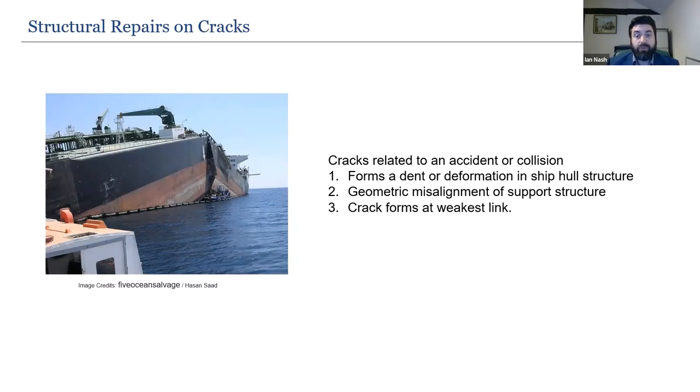While repair techniques have remained static, structural composites can offer a cost-competitive alternative that's fast, non-disruptive and delivers improved strength. Steel ship structures develop cracks as a result of their welded construction, material imperfections, loading conditions, fatigue and corrosion. Welded ship structures are susceptible to damage during construction and operation from design inadequacies, material selection imperfections, improper welding, fatigue and corrosion. Crack formation appears unavoidable given the uncontrolled variables involved, especially the use of high tensile strength steel for the hull structure.